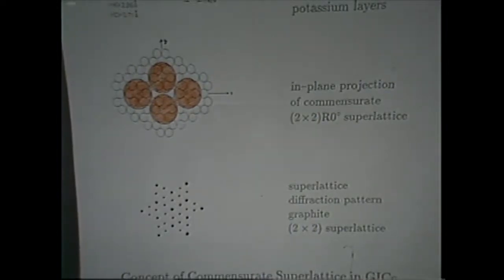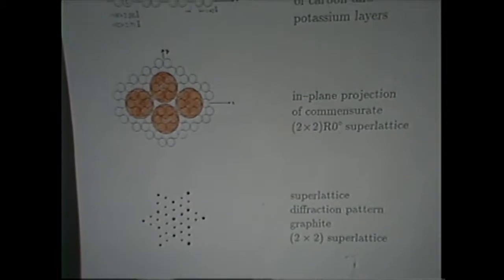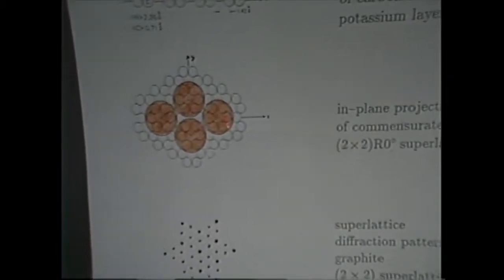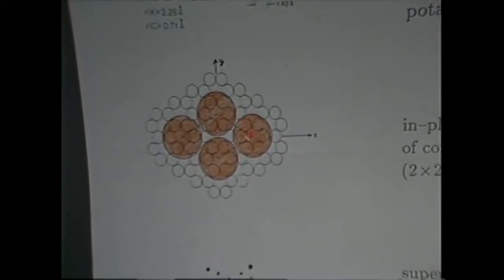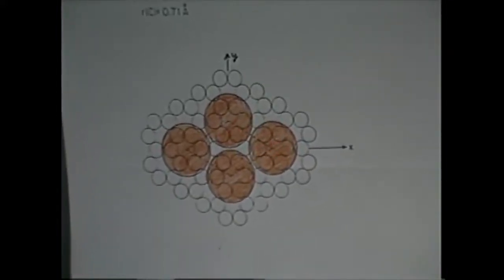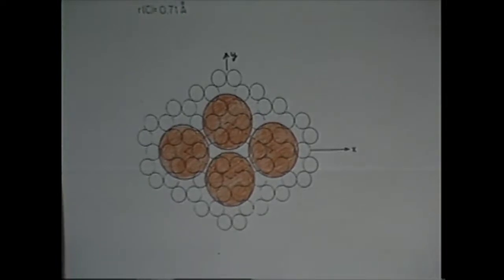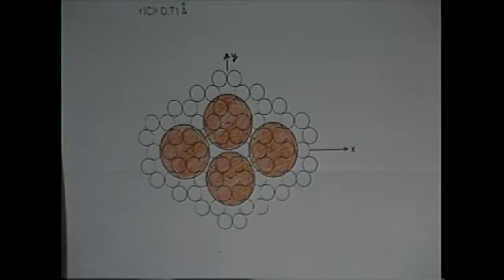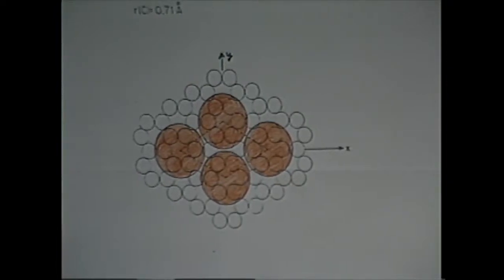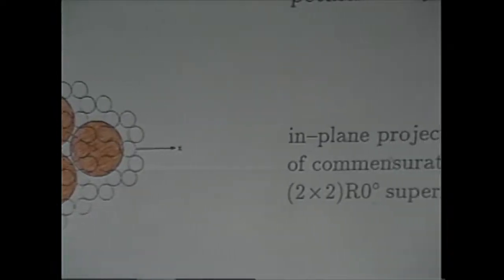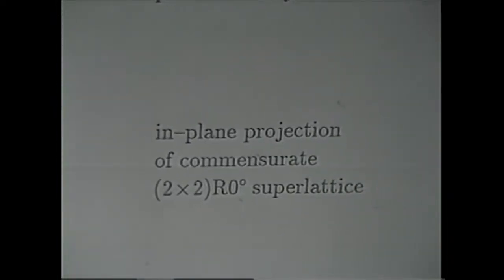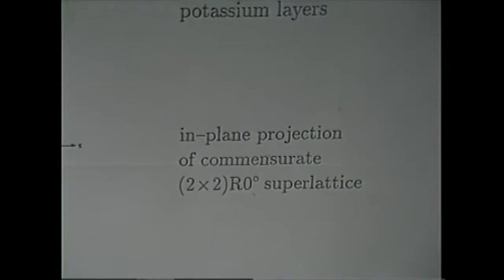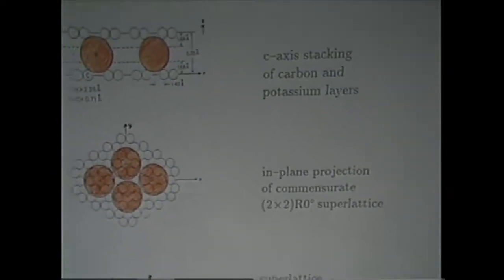Well, here is a commensurate structure of potassium on graphite. It forms a 2 by 2 superlattice in plane. 2 by 2 meaning that the unit cell this way is twice the length of the unit cell of the graphite itself. Now, why does it form a commensurate lattice? There are two forces that are important. One is that the potassiums, or the intercalate in general, likes to assume a near neighbor distance that's almost the same as is in its native material. It's a two-dimensional material, and the potential minimum for the attraction of the atoms is almost unchanged from what it is in the pristine material.